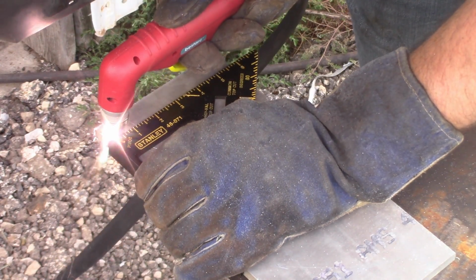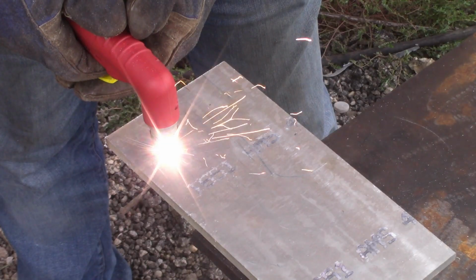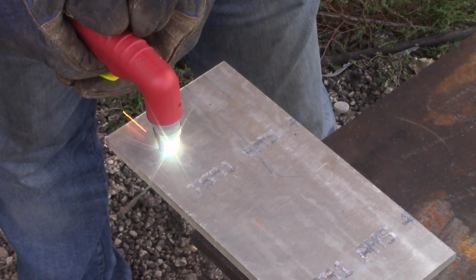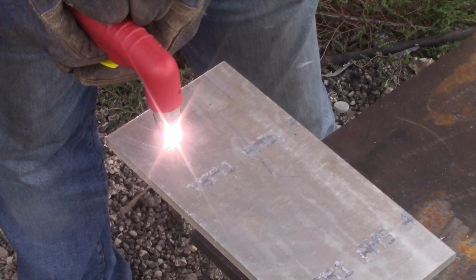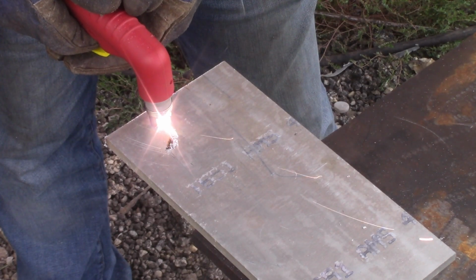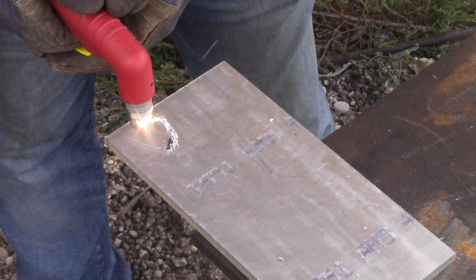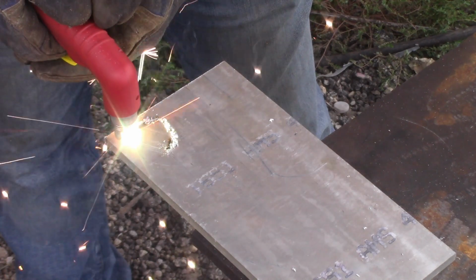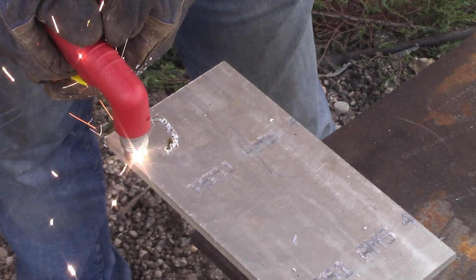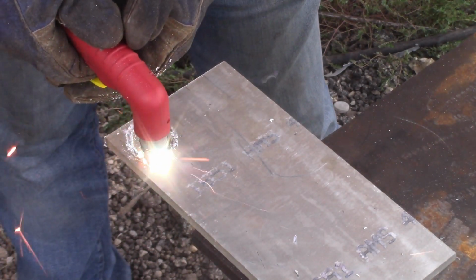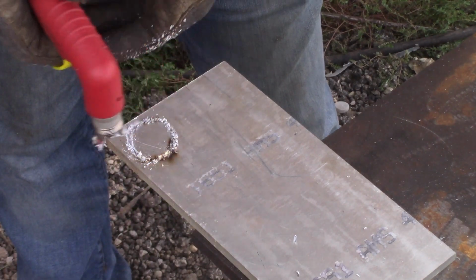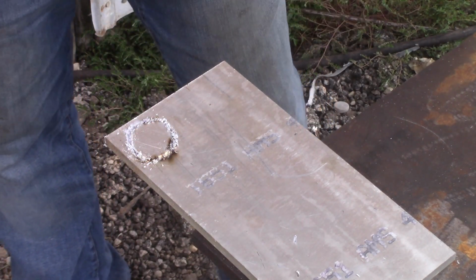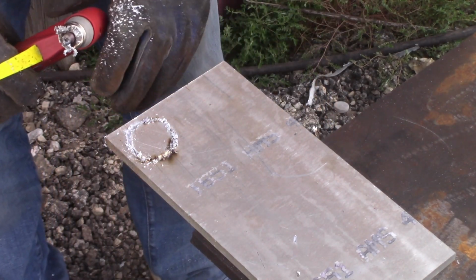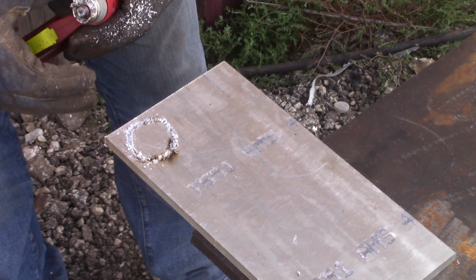It cut very easily on straight cuts, but when I tried to pierce through it, it didn't work so well. Looking back at the footage, I should have tried to angle the torch more to start the pierce so it would blow the material to the side. Instead, it just blew it straight up all over the consumables and actually burned through my cut guide as well. A fair amount of it sprayed all over my gloves too, so let that be a lesson to you about the importance of wearing your PPE.